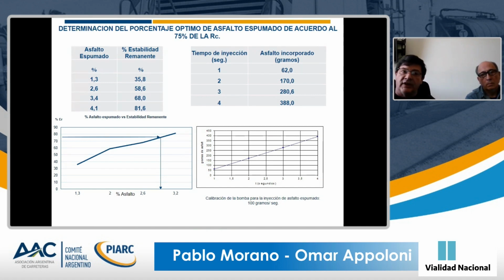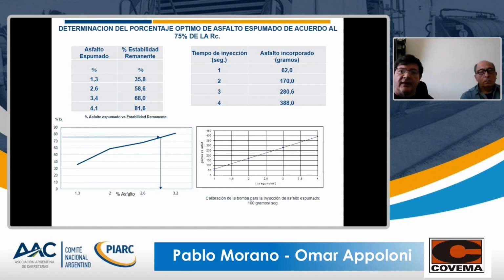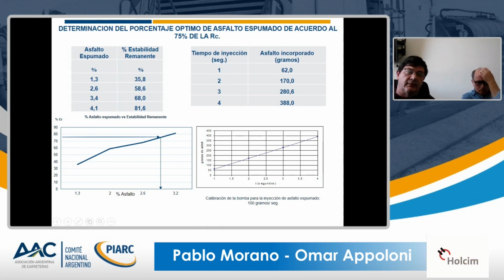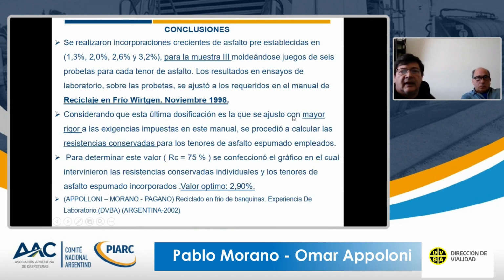And here, based on the foam percentage in the asphalt, we started checking the remnant stability to get the percentage of asphalt that we were going to use for remnant stability. And the other process that we needed to do in order to know how much asphalt we needed to have in our mix was injection time, to know how many grams of asphalt we were going to incorporate to the mix.